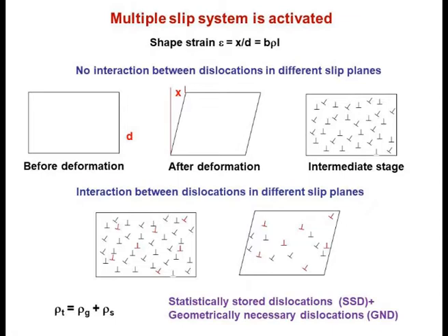But it can happen that dislocations interact during the motion. When they interact, some of them will become sessile dislocations, some will become forest dislocations, and these are the dislocations which we are going to see in the material, right? So finally we will be left with some dislocations, while others have disappeared. Some are the red ones which I used to show that they have come out of dislocation reactions, others are the original dislocations which are stuck there. So this is the sort of microstructure which will come.